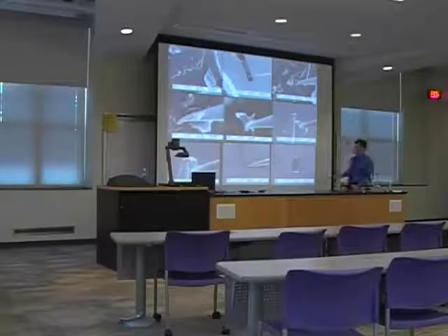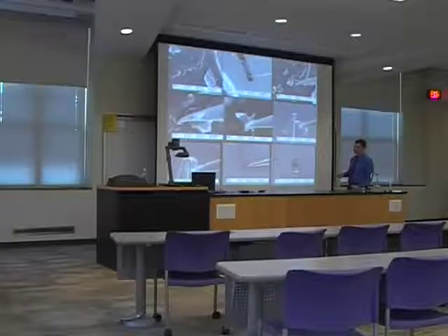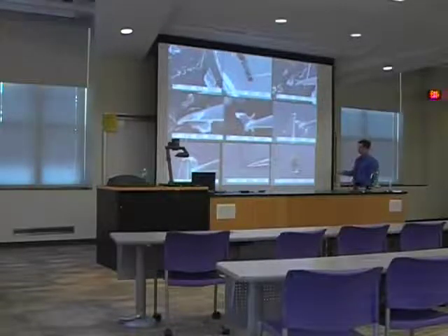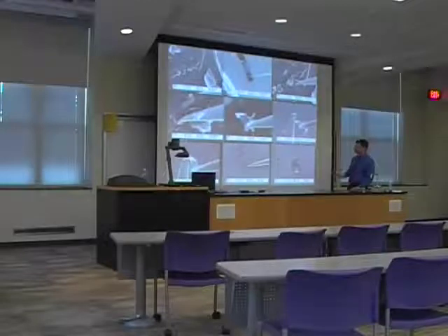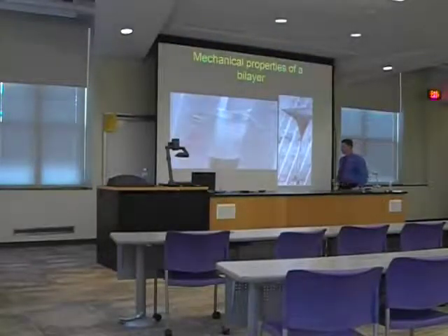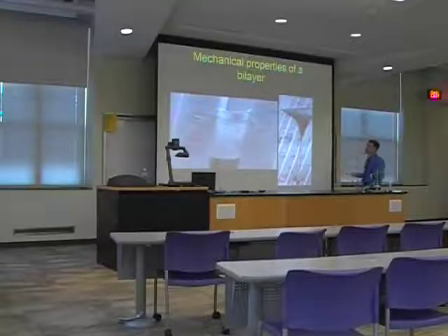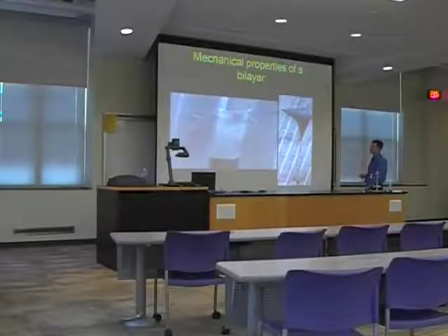Or another option would be just to drop it on the substrate. And that's what I did. I just attached it to the substrate and then changed the polarity on the probe. And this is the layer of graphene on the substrate at the location where I want to put it. These are marks for electron beam lithography. After that, you can fabricate the device lithographically. And here is, let's say, a double layer, 2 atomic layers of graphene between the trenches.